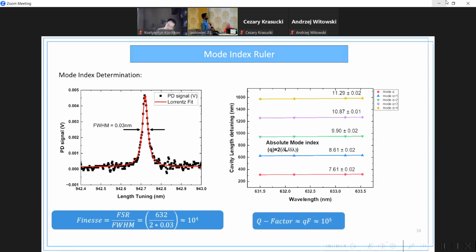And if you measure the position of each mode as you tune the wavelength, each of these lines corresponds to a cavity mode. So from the slope of such a curve, you can also calculate the absolute mode index. What I was talking about previously were the relative mode indices, and these are the absolute mode indices of the cavity.